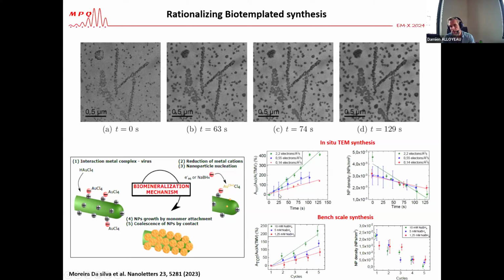Now, what's going on when you increase the dose rate? You increase the dose rate, you increase the concentration of reducing agent, you increase obviously the growth speed. But what is interesting is that when you increase the growth rate, you also increase at the very beginning of the experiment the density of nanoparticles. So you have a very high burst of nucleation at very high concentration of reducing agent. But then the density decreases because very rapidly we have those coalescence mechanisms.